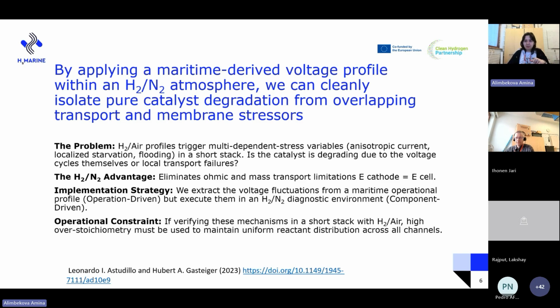Now let's look at the choice between hydrogen-air or hydrogen-nitrogen ASTs, because during real-time operation, it will be working under hydrogen air conditions, and the stresses in these conditions are dependent on different stress variables. If we run a maritime dynamic profile using a short stack with the hydrogen-air feed, the degradation we see is quite complex, and because the current distribution is different across the stack, the local relative humidity fluctuates, and you could get local reactant starvation or flooding on the electrodes.